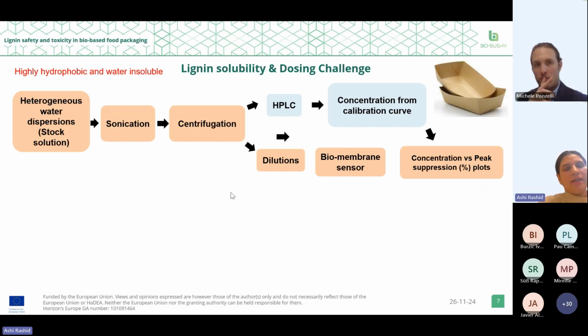So here, we know that lignin is very poorly water soluble. Therefore, dosing lignin to the biomembrane sensor in aqueous medium was a great challenge to us, and we dealt with it by making heterogeneous water dispersions of lignin by ultrasonication, and then the supernatants were subjected to the biomembrane sensor to see the interactions of the solubilized lignin with the biomembrane. The same supernatants were also analyzed on the HPLC for measurement of the actual amount of lignin in solubilized form in the supernatant.